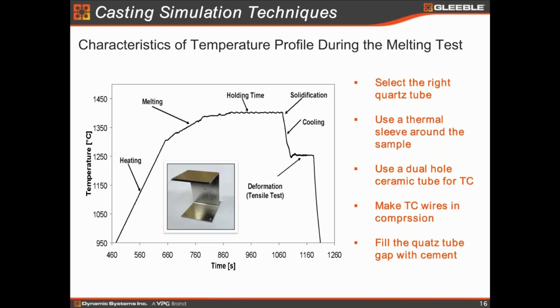We provide a cement to every Gleeble user. What you do is, you mix the cement with water to make a mushy thing. And then you can cover this cement over the whole slot of the quartz tube. Okay. But you need to get rid of the water or moisture within the cement before you do the testing. So the way you could do it is just heat the sample manually to, let's say, 100 plus degrees C until the water is evaporated, so the cement becomes solid.